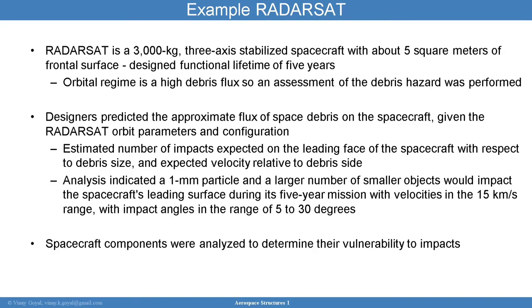The example here is a radar sat. It's a 3,000 kilogram spacecraft. In this case, you have a three-axis stabilized spacecraft with about 5 square meters of frontal surface, which is designed functionally for 5 years. The orbital regime where it's at is high debris, so an assessment was required of this debris hazard. Designers predicted the approximate flux of space debris on the spacecraft, given these orbit parameters and configuration, and they needed to do something about that.